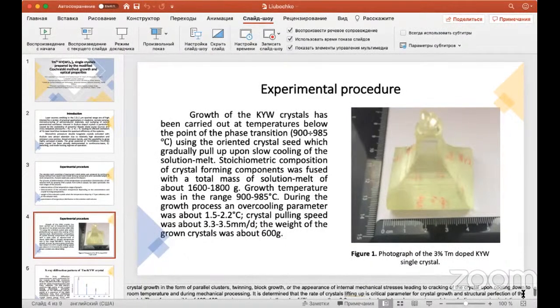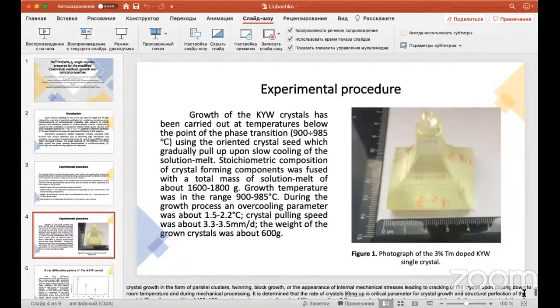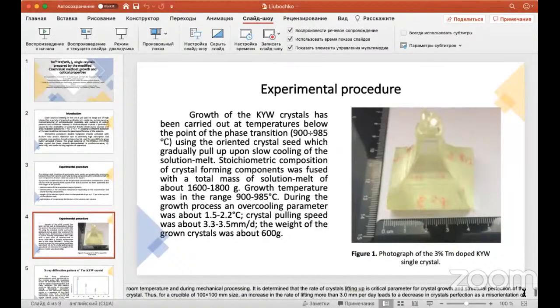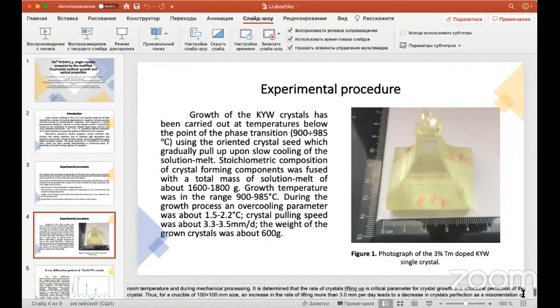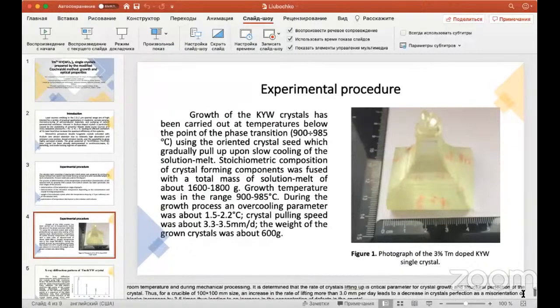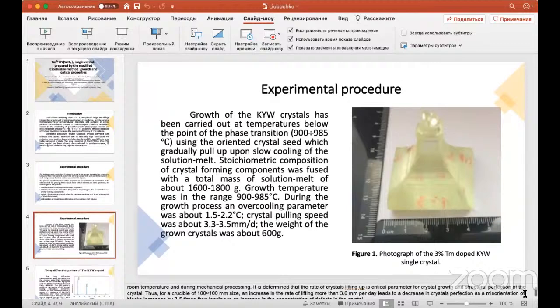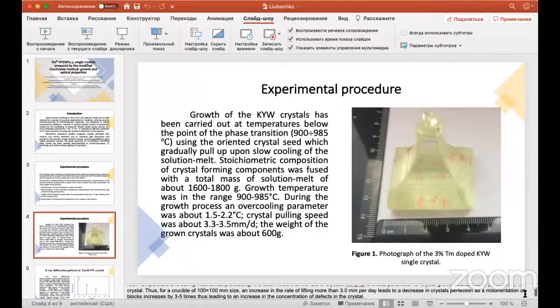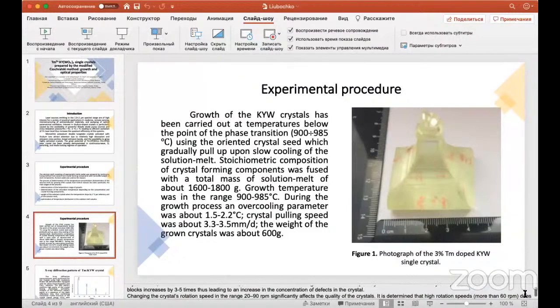It is determined that the rate of crystal lifting up is a critical parameter for all crystal growth and the structural perfection of the crystals. Thus, for a crucible of 100 by 100 millimeter size, an increase in the rate of lifting of more than 3 millimeters per day leads to a decrease in crystal perfection, with the misorientation of blocks increasing by 3–5 times, thus leading to an increase in the concentration of defects in the crystals.